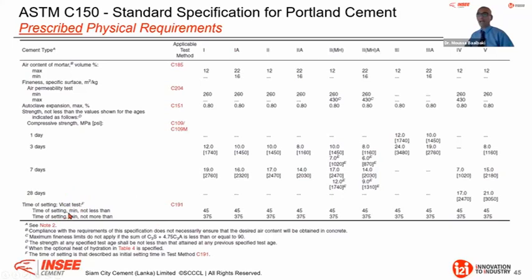Again, for setting time, here they have a requirement of 45 minutes minimum. Okay, and they don't specify final setting, only initial setting, with a minimum and not longer than 375 minutes. Therefore, minimum and maximum, these are the two requirements.